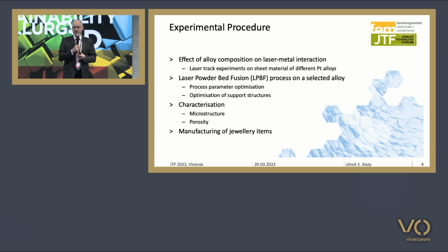Then we used a commercially available alloy by C. Hafner to do some laser powder bed fusion experiments. We did a small parameter optimization, and I will show you an example about how the support structures influence the result you obtain. We also did a small optimization of such support structures, and of course we did the characterization by microstructure and porosity, and manufactured some jewelry items as examples.